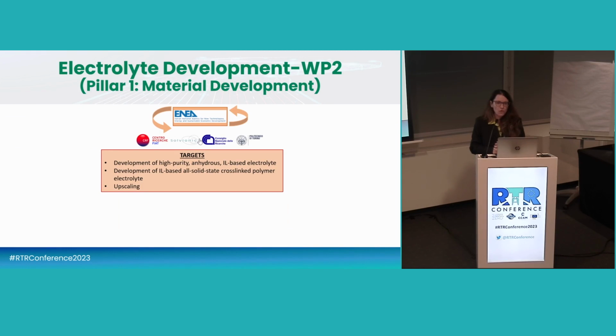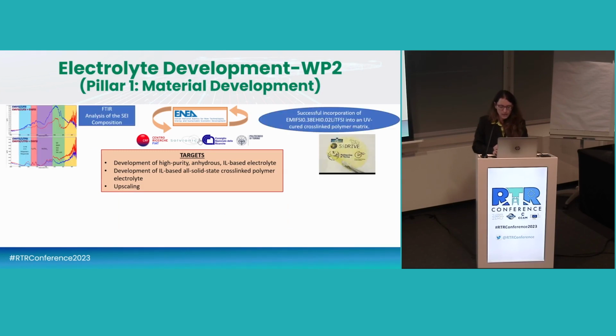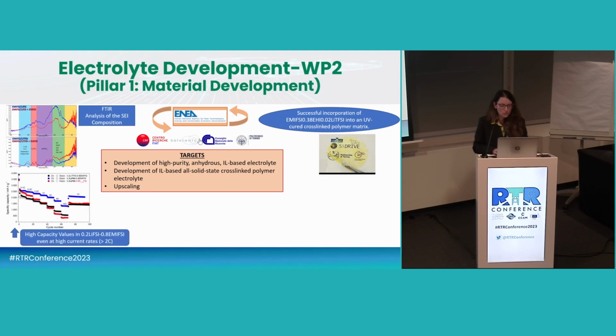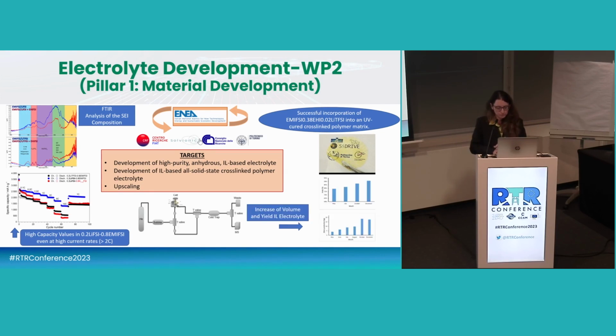The work package 2 is focused on the development of the ionic liquid-based electrolyte. This work package is led by the ENEA Research Center, and this was a very strong cooperation between the ENEA that found which was the optimal composition of the ionic liquid electrolyte that was allowing us to have the target of high current rates. So our target for this ionic liquid electrolyte was to have this kind of performances, but from the point of view of the safety, with the collaboration of the Politecnico di Torino, we were able to incorporate in a polymeric matrix this ionic liquid that the ENEA developed.